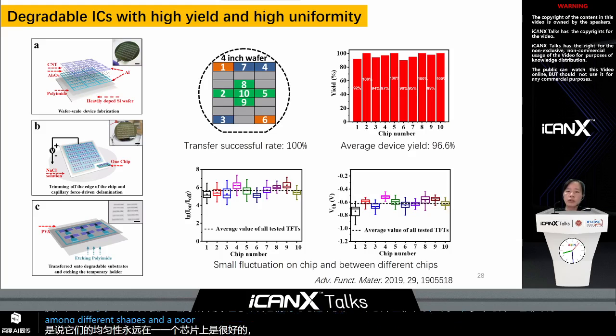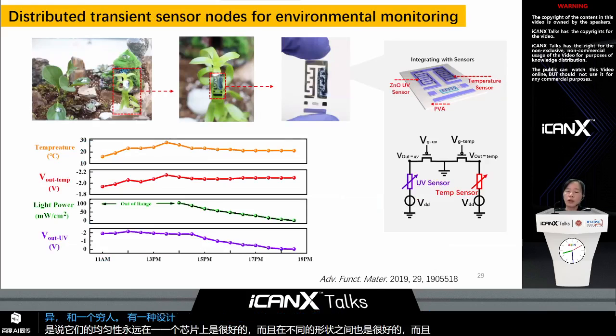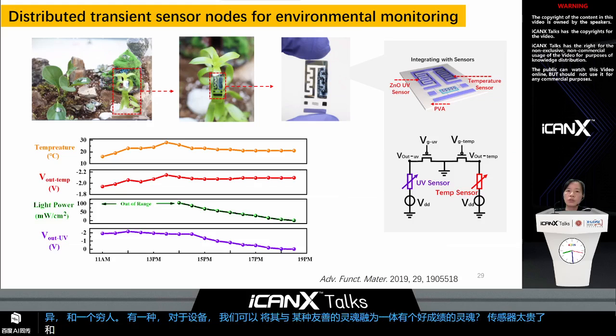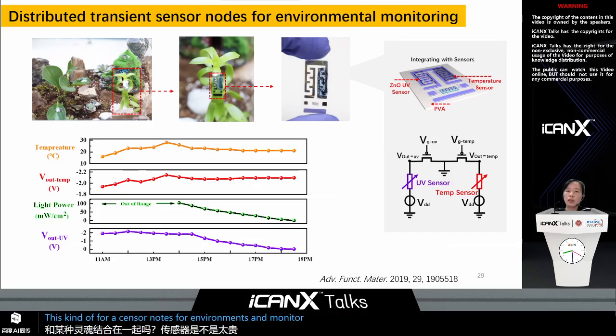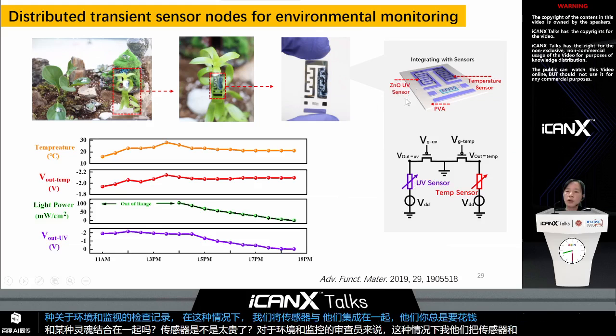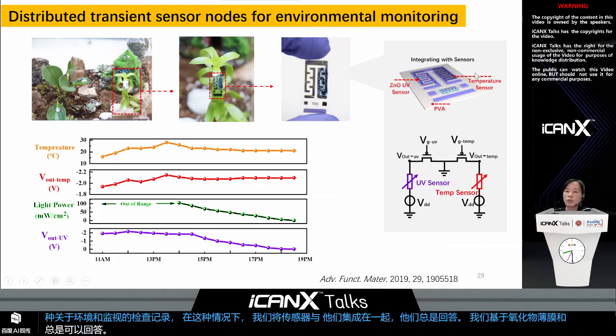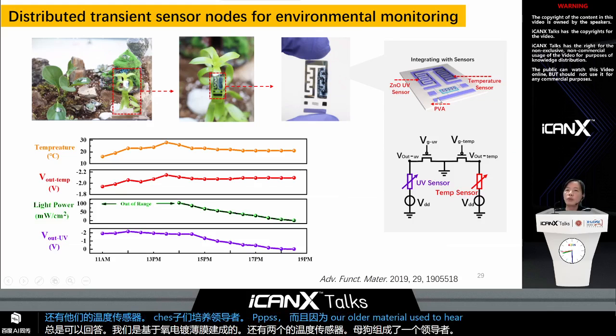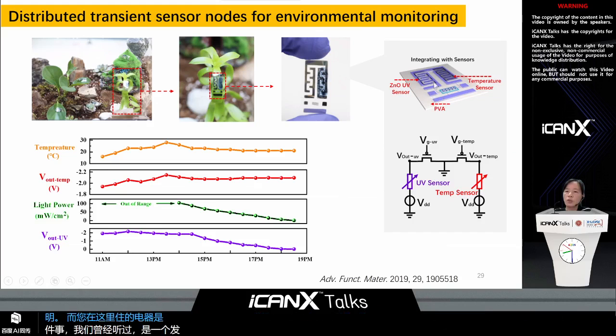And for this kind of device, we can integrate it with some degradable sensors to construct sensor nodes for environment monitoring. In this case, we integrated our devices with a UV sensor, which is constructed based on zinc oxide thin films, and also a temperature sensor, which is constructed with PEDOT:PSS. And all the materials used here are degradable: the metal we used is aluminum, and the dielectric we used is aluminum oxide.